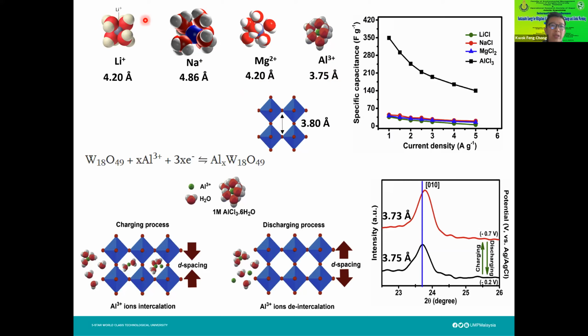And the lithium, sodium, and magnesium, because their size is bigger, are not able to intercalate into the crystal structure. We can see that from the charge storage, whereby the specific capacitance for the aluminum chloride is very high as compared to the rest of the cations.